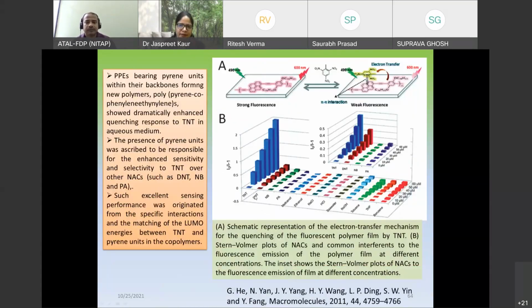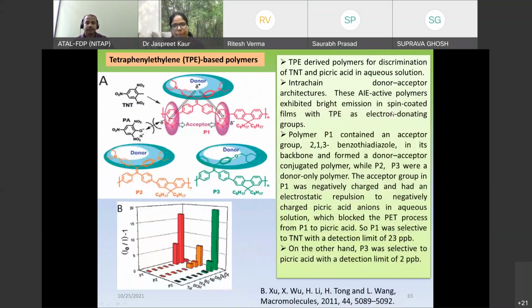Similarly, the pyrene based PPE derivatives, which have the pyrene unit within their backbones, form a new type of conjugated polymers, which helps in better sensitivity for TNT over the other nitroaromatic compounds. This sensing performance is because of the special interactions between the LUMO energies of the TNT and the pyrene groups, which are present as a copolymer in the PPE backbone. So this is strong fluorescence, weak fluorescence. It means pi stacking interactions are there, and this is a type of sensor which is PPE based.